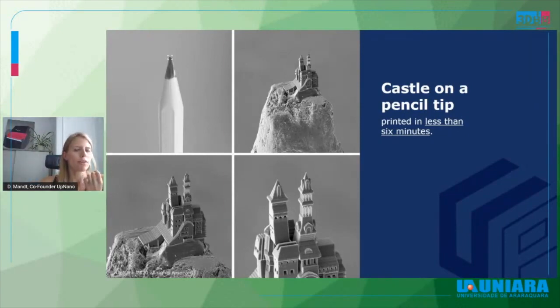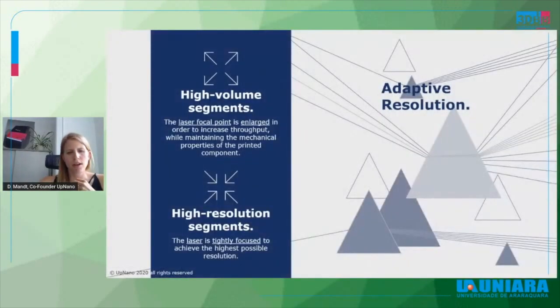And therefore, one of the key features, which is also patented by UpNano, is the adaptive resolution process. Offering this adaptive resolution, we can distinguish between areas of high resolution, like again, the pillars, windows, stairs, and focus the laser very precisely to achieve this fine resolution and these fine features. But when having the bulk material and the inner material, we can enlarge the laser beam by a factor of up to 10.